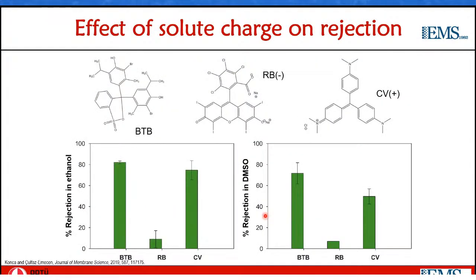And the next thing we did was we tried to see the performance of the membranes with two different probes of similar size to bromothymol blue, but different charge. Here, rose bengal with a negative charge and crystal violet with a positive charge. We did this again in ethanol and in dimethyl sulfoxide, which is actually quite a harsh solvent, a polar aprotic solvent that dissolves many membrane polymers and also swells cellulose to a significant extent, but we observed no performance loss for at least weeks of filtration in any of our experiments.